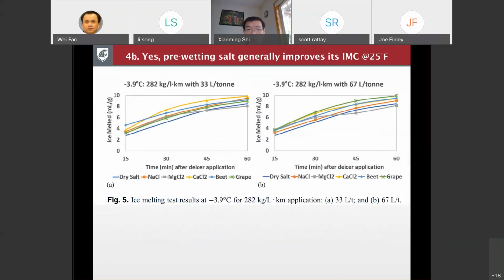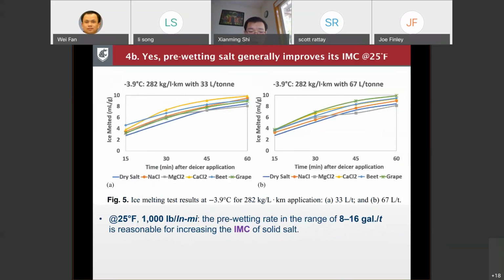mobility benefits. The first one is, yes, the pre-wet salt actually generally improved their ice melting capacity at 25 degrees. Here, of course, we have to look at which pavement temperature, 25 degrees. And also, we ended up using a higher than usual application rate of pre-wet salt because otherwise, there's simply not much salt to be applied on that ice layer, and then the error range will be too high. So in the lab, we had to go with a higher number. That's the limitation of the lab test, but it still tells us, at relatively warm temperature of the pavement, the pre-wetting actually helps the ice melting.